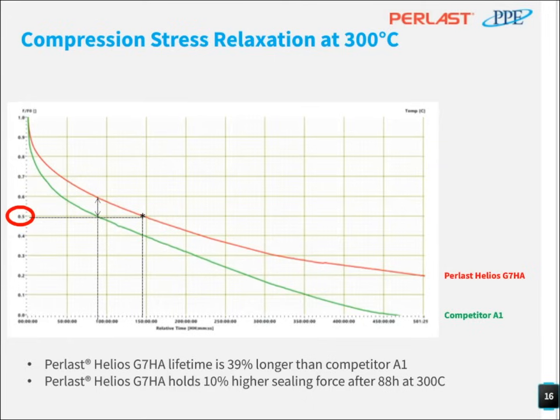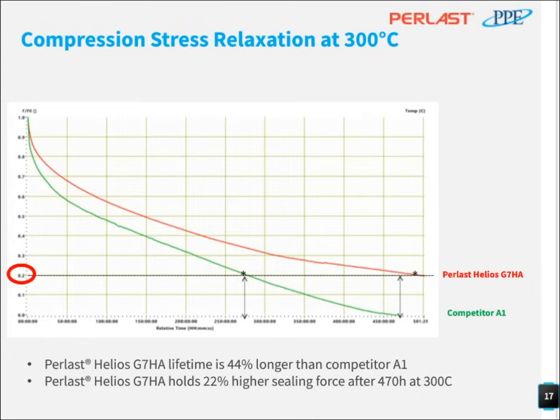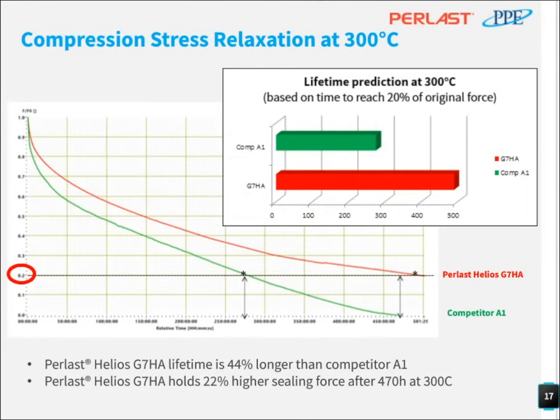But as I said in the previous slide, even 20% of the initial force would be enough to hold the vacuum in most of the cases. And if you compare the time to reach 20% of the force, the gap between Perlast G7HA and the competition gets even bigger. Our material offers almost 45% longer lifetime at 300 degrees C in the test conditions, which is dry air.